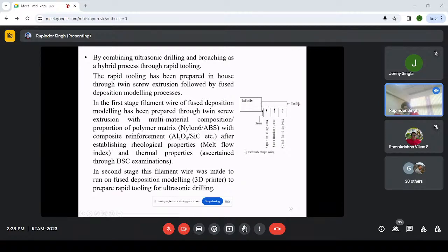So whenever I am ultrasonic drilling this part, once the part is entered inside, now this zone, outside zone, is having coarse grains of the alumina. Once it enters inside, these abrasive grains are relatively finer, and once they move further, the more fine grains were there. So coarse grain, fine grains, and very fine grains.